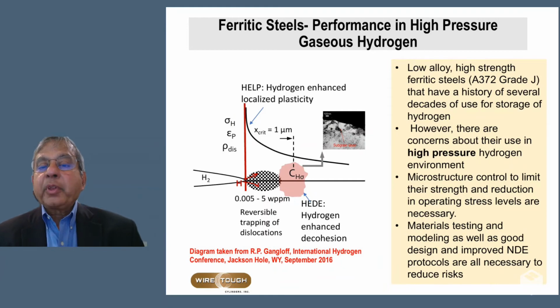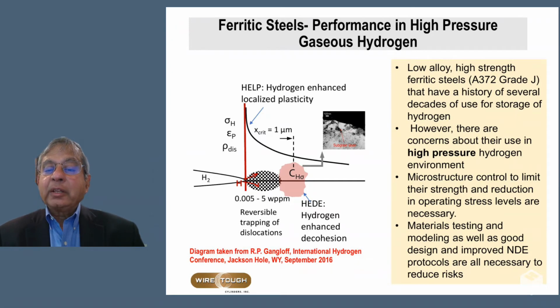degradation mechanisms. The steels that are used are low alloy, high-strength ferritic steels, A372 grade J, that has a history of several decades of use for storage of hydrogen, although at low pressures. However, there are concerns about their use in the high-pressure hydrogen environment. So microstructure control to limit their strength and reduction in operating stress levels are necessary. Materials testing and modeling, as well as good design and improved NDE protocols, are all necessary to reduce the risks.